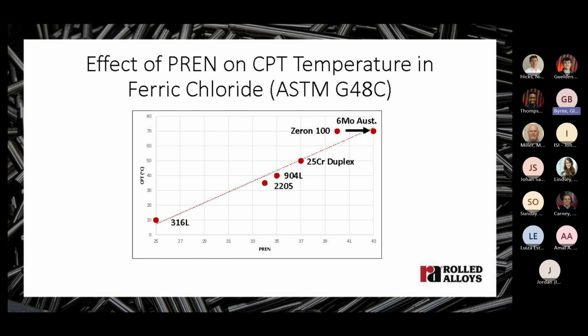These tests provided a ranking of alloys, but there was no reliable correlation between these tests and real seawater service performance. In the early 1980s, companies like Shell were looking to replace copper alloys with stainless steels in seawater cooling and fire protection systems on offshore platforms. Their approach was to initiate a 4-year-long research program of testing of stainless steels and nickel alloys in the North Sea. They based their material selection strategy for future projects on the results of this work.